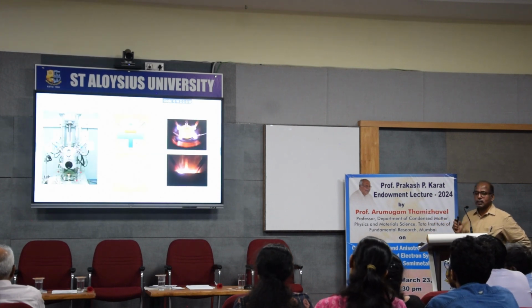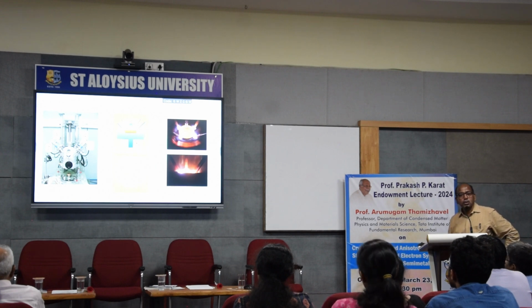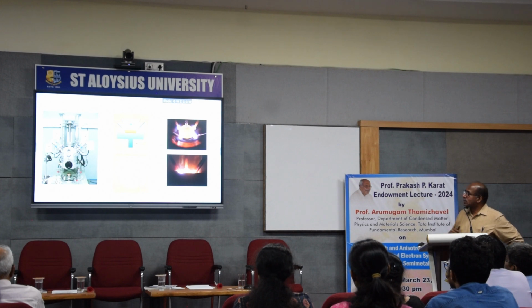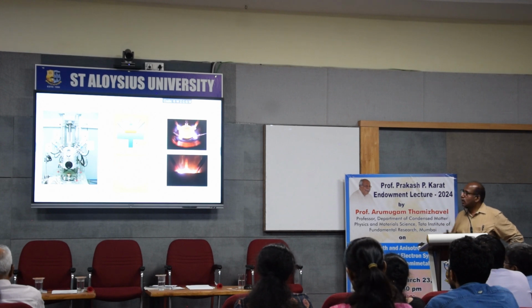And we have a furnace in our lab to grow intermetallic compounds by the arc melting method. We don't have a much larger furnace. It's a very small furnace where we can melt about 10 to 15 grams of sample. And here we use these electric arcs to melt the sample.